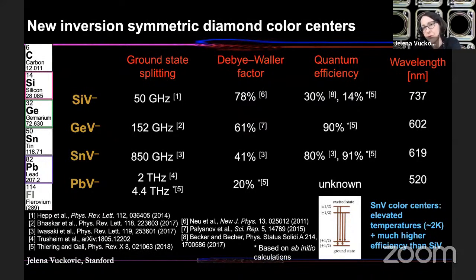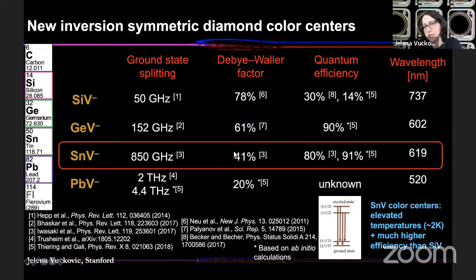And that means that you can actually, as opposed to nitrogen vacancy center in diamond, bring it closer to surfaces, embed it easier in the structures, and make photonics more scalable in this platform. Initial experiments have been done on silicon vacancies. Then there was quite a lot of work on germanium vacancies, and recently we and a few other groups have focused primarily on tin vacancies in diamond.